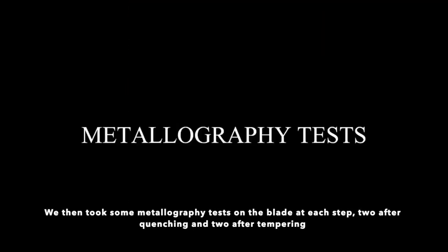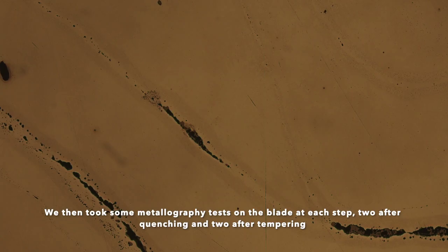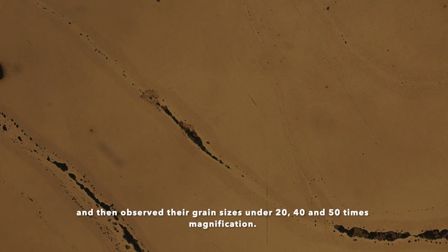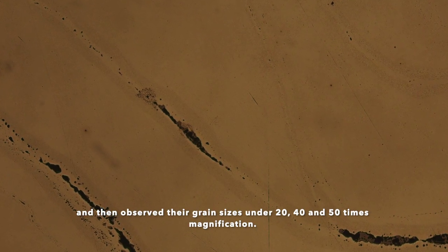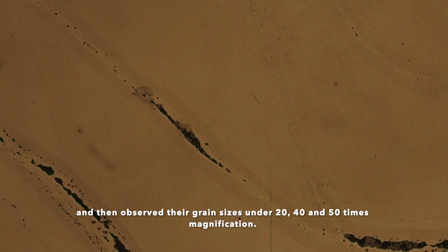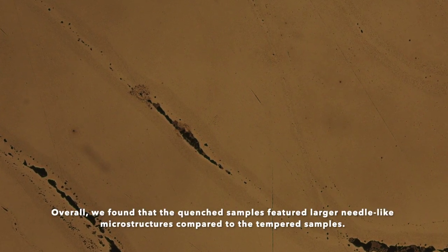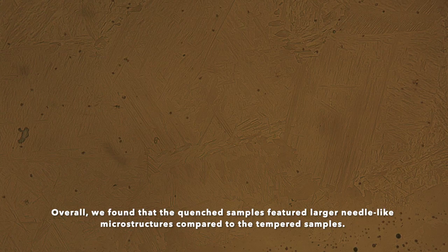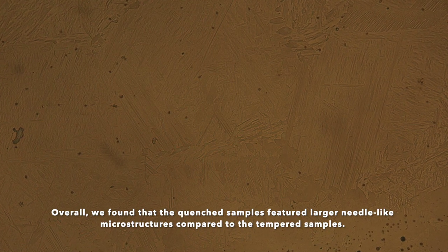We then took some metallography tests on the blade at each step, 2 after quenching and 2 after tempering, and then observed their grain sizes under 20, 40, and 50 times magnification. Overall, we found that the quenched samples featured larger needle-like microstructures compared to the tempered samples.